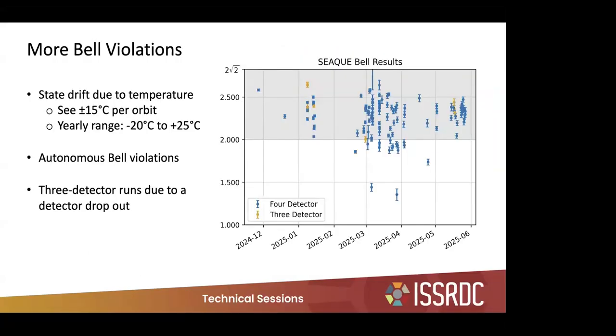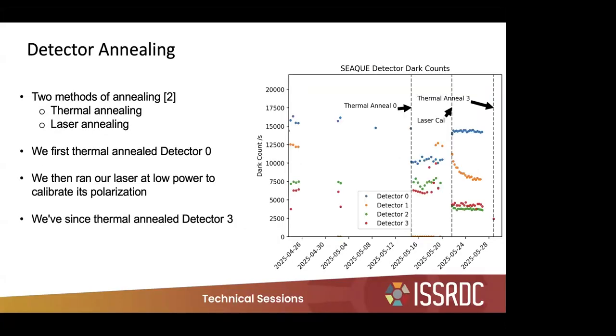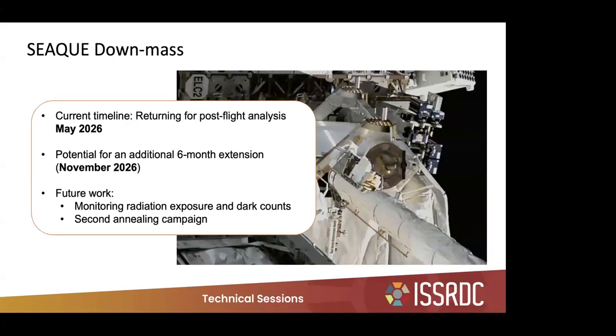Since then, we've been able to take a lot more Bell violations, as well as monitor our detector dark counts as the radiation increased the dark counts, and perform some detector annealing via two methods: thermal annealing and laser annealing. So the current timeline is that SEAQUE will be returning for post-flight analysis in May of 2026, but there is a potential for an additional 6-month extension, which would bring it to November of 2026. This would allow us more time monitoring radiation exposure on the detectors and doing some more annealing tests.